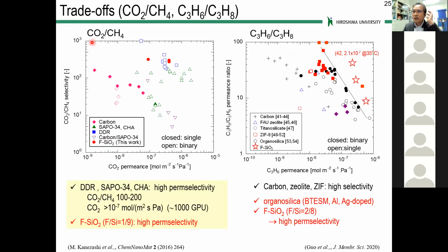This is a trade-off plot for CO2/methane and propylene/propane separations. Reportedly, zeolite membranes such as DDR or SAPO-34 and CHA chabasite-type membranes are plotted here with triangles and squares, and show very high permeance ratio and permeance. Our fluorine-doped silica membrane is plotted here, showing high perm-selectivity similar to zeolite membranes.